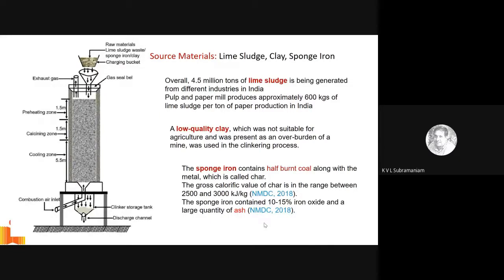Now, what does a kiln do? A kiln basically is nothing but a large tube, which allows me to develop this gradation in temperature. And that's what this vertical kiln did. Basically at the bottom end, you have the high temperature heat source. At the top end is where you introduce the charged material. Charged material, remember, has to have a source of calcium. It has to have a source of silica. The material has to move slowly through the drum and basically be slowly subjected to a higher and higher temperature. And it has to be subjected to a temperature up to about 1500 degrees Celsius,